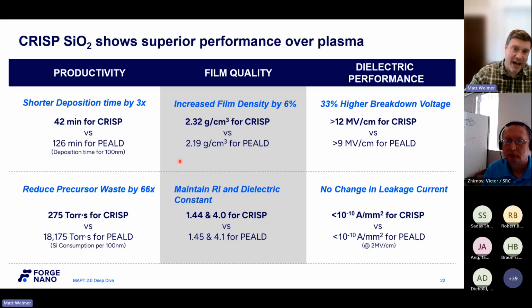In silica, probably not, but in metal films, this starts to get a bit important. However, this next set are perhaps the most important ones to me. Our density is about 2.3. For this process, it was about 2.2. So we're more dense, which is great. If you look at the Ri, the dielectric constant, we're a little bit more ideal on both.